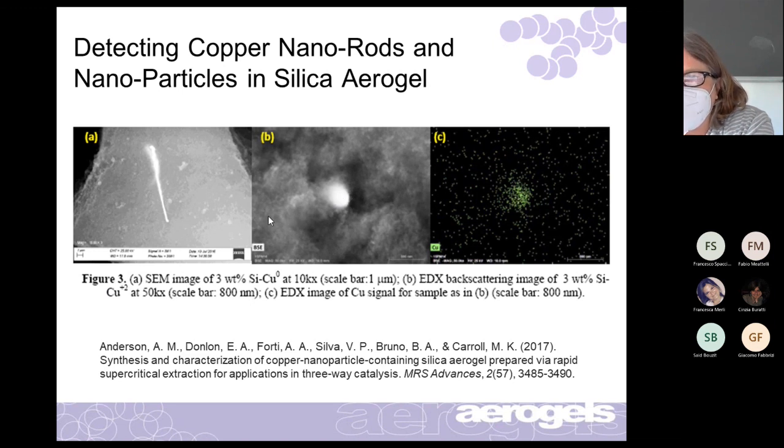And it's possible that some of this is the smaller nanoparticles that are what we actually put in. But it's also possible that this is just scatter in the signal. We cannot really detect that well. So it could be that we have a lot of the particles, and then in some places they join together. Could be not. We're at the limits of detection for the scanning electron microscope in this case. But this is an example of some of the information you can get from this.